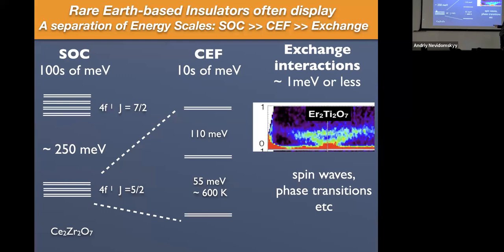This is a Kramers ion with an odd number of electrons, so that's going to give us 3 doublets. And then the next excited state is J equals 7/2. It's going to give us 4 doublets there. And then we're going to have the effect of the crystal electric field. So the cerium-3+ is not in vacuum. It's not in outer space. It's sitting 2 or 3 angstroms away from these very strongly electronegative oxygen ions. So it's feeling this very strong electronegative environment, and that's going to take these 6 states, which would otherwise be degenerate, and break them up into 3 doublets. But the crystal field energy scale is about an order of magnitude lower. It's of order 10 meV.